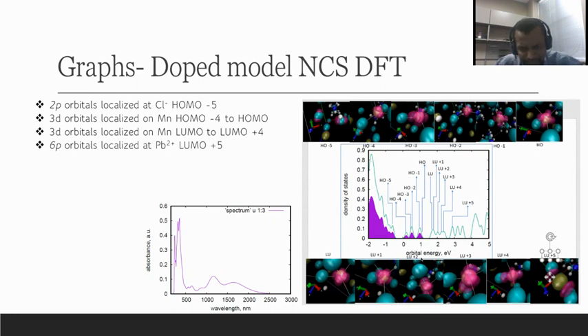And then also for the LUMO, on the bottom, we see that from LUMO to LUMO +4, they have the same shapes as the ones from HOMO -4 to HOMO. And right after that, at LUMO +5, we have the orbitals localized at the lead. So that also confirms what we said earlier about the spin-polarized DFT.